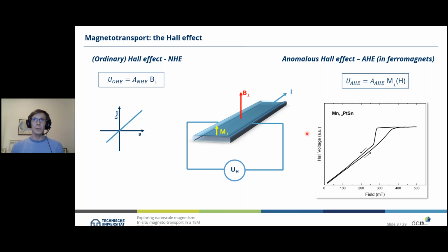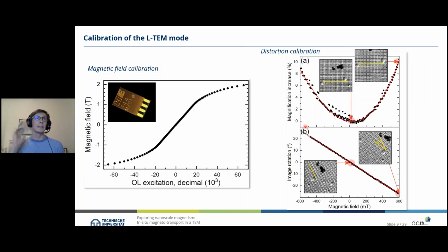And in the electron microscope, this can be done by using the objective lens. The objective lens is a quite strong magnetic lens, which can apply magnetic fields up to 2 Tesla out of plane with respect to the sample, similar to what is shown here in the sketch in the center. But if we change the magnetic field, or the excitation of our objective lens, of course, the TEM in general is not made for that. So there are different things we need to take care of.